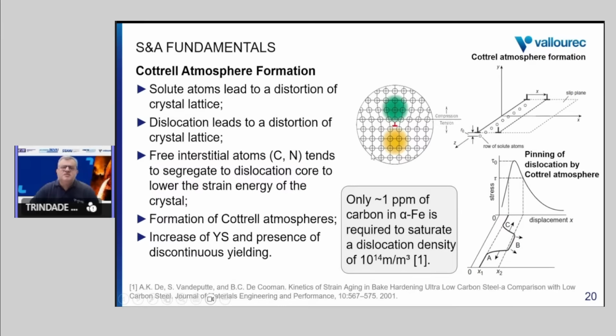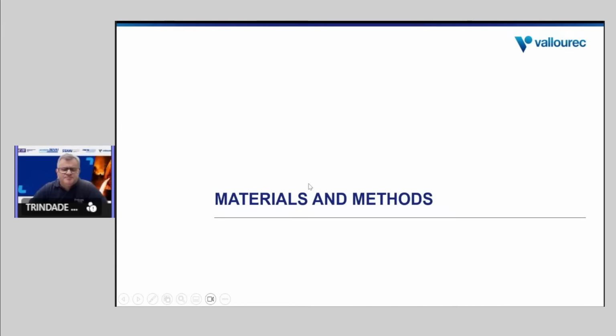Once we have this saturation, we have a phenomenon called pinning of dislocation by Cottrell atmosphere. This is what happens during the aging. So the Cottrell atmosphere is pinning the dislocation movement and then increasing the material strength.